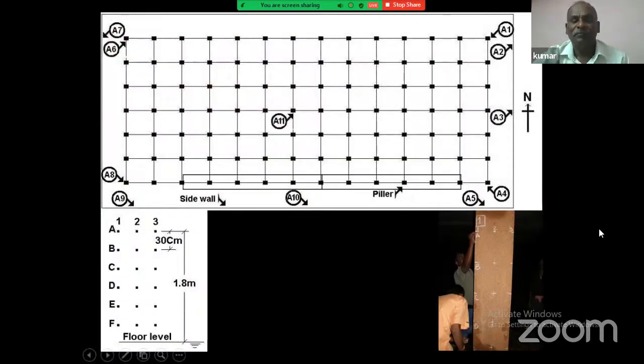This is the way we have made the condition assessment. For example, in the structure, we have made grids at uniform intervals. From these grid points, we kept our reference electrodes and moved along them and measured, and we gave the data to our software and found the mapping.